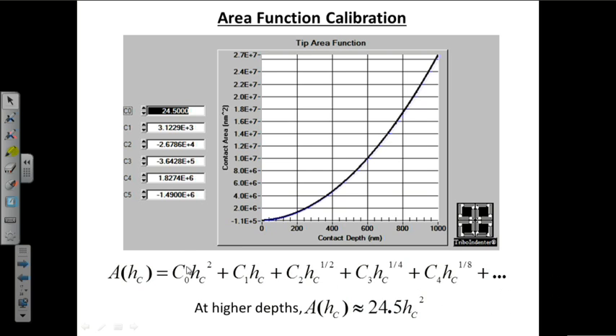And the coefficients of these expressions, such as C0, C1, C2, etc., are given on the left hand side of the graph. It turns out that if we do higher load indents, that means at higher depths, that is at higher contact depths hc, the first term of this polynomial dominates the rest of the terms, and therefore, we can neglect the rest of the terms, and we say that area, which is a function of contact depth, is almost equal to 24.5 hc squared, and this contact depth and contact area could be used to calculate the hardness and the reduced modulus by using the formulas which were described in previous slides.